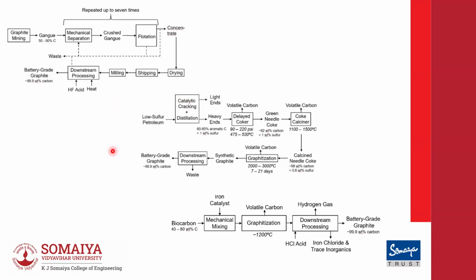If we look at synthetic graphite, I can start off with a low sulfur petroleum material, which is a hydrocarbon. Then I go for catalytic cracking distillation, which means technology driven. Then if you see over here, I need to heat it at 1500 degrees. I need to convert it to the graphite structure, which is your layered hexagonal layers. I need to go up to 3000 degrees Celsius, and that too for prolonged times, 7 to 21 days. So you can imagine how much energy I need for it.